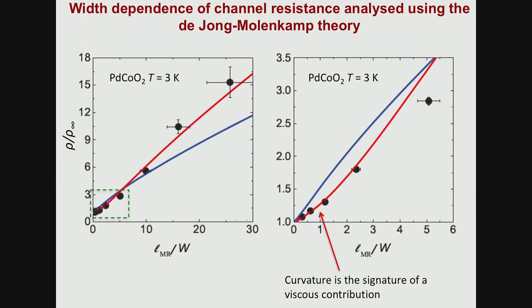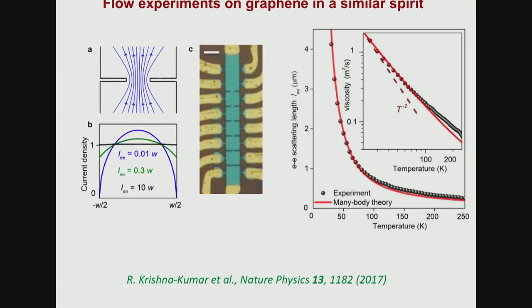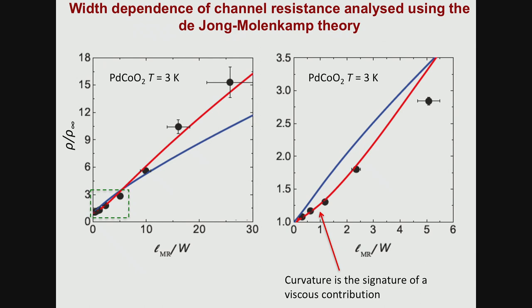All of that together was, you know, whether people wish to believe that line of argument or not, that comparison between kinetic theory and experiment led us to say, we're seeing a signal here which can be better described by including a viscous term than not. And it's just what you were asking about earlier. Again, it's a relatively small extra effect which is being seen that we believe there's a hydrodynamic explanation for. So we published as well. And actually, the 2 graphene experiments and ours were all done totally independently. I don't think we knew about them, and they were all published in the same issue.